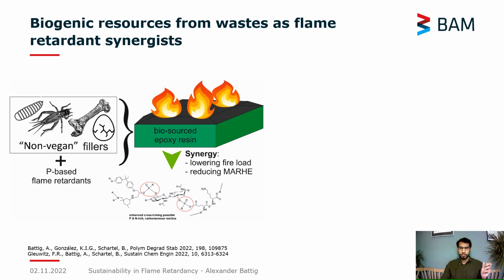These insect fillers, using black soldier fly, using house crickets, but also using bone meal and eggshells, were studied as bio-based fillers for epoxy resins using phosphorus flame retardants. That was our goal in this paper. And what we saw is that there's actually a synergistic effect between these two. We quantified the synergy, and we saw a lowering of fire load. We saw a synergistic reduction of the maximum average rate of heat emission. So there's a slowing down of the fire when you add these compounds because they don't burn quite as well. And more importantly, they interact with phosphorus-based flame retardants to create a very thick char layer and reduce the total heat evolved of the material.